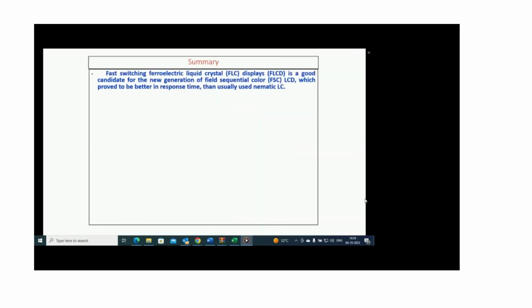And then, in summary, we also mentioned fast ferroelectric liquid crystals, which are a good candidate for a new generation of field sequential color LCD, which proved to be better in response times than nematic LCD. We solved many problems already in ferroelectric liquid crystals. By using photoalignment, we demonstrated different types of regimes and different electro-optical modes. And we are now concentrating on making prototypes and arranging mass production of ISO-dye photoaligned ferroelectric liquid crystal devices. So prototypes of ferroelectric liquid crystal devices can include not only microdisplays, but also 2D, 3D displays, and so on.